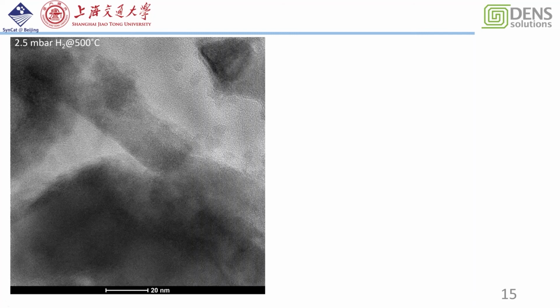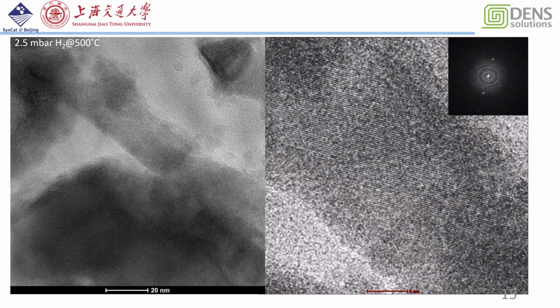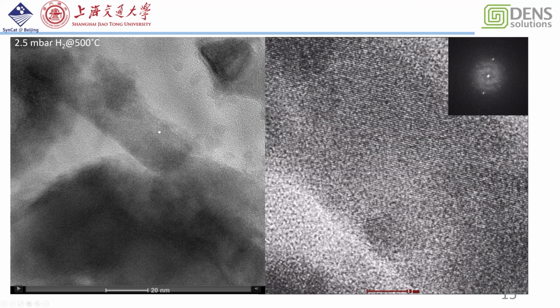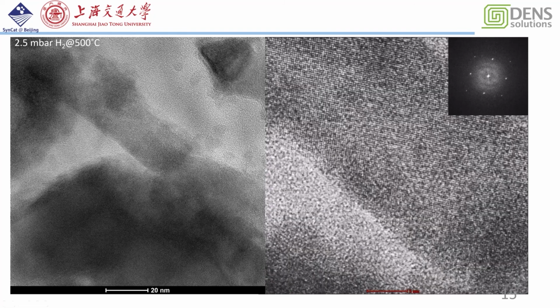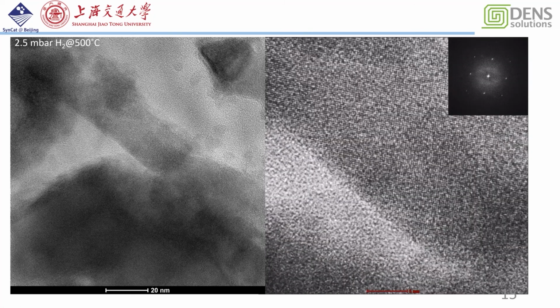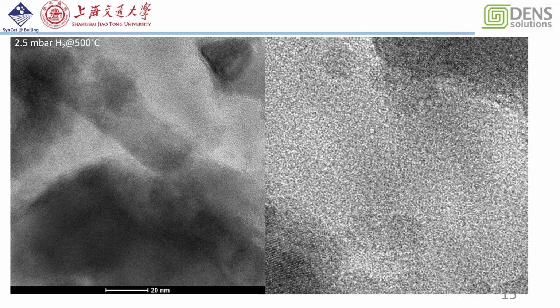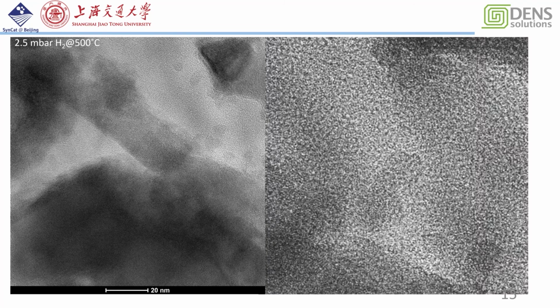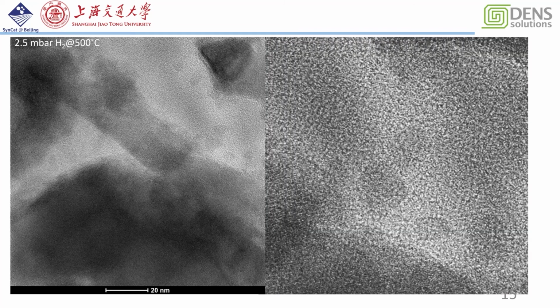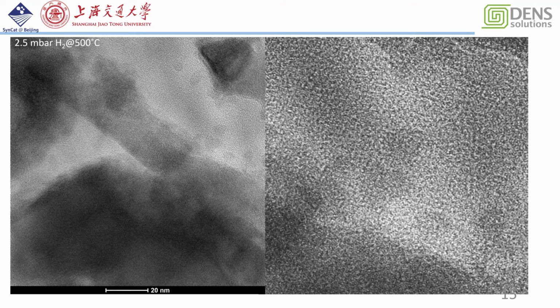But if we take the central part of this, we can see that in some parts the reduction is also happening as a topochemical reaction, directly transformed from hematite to magnetite. But we notice in a different part the situation is very different. We can see the growth of a particle out of the parent material, and this particle is very mobile and just disperses all around the chip. It looks like, although the topochemical transition can happen under some reaction conditions, the deformation and degradation of the iron oxide in the presence of hydrogen is the predominant process during the reduction.